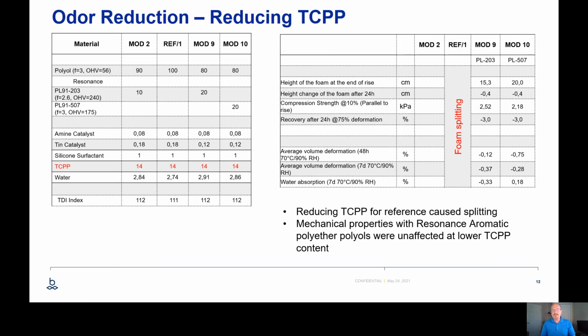So we went a little over 20% reduction in the TCPP because we figured it has to be a fairly large reduction in TCPP to affect the odor of a system, considering that TCPP has a relatively low vapor pressure, so it must take a lot to create any kind of odor. The only delta we saw with this particular system is the reference that we're using versus the 14 parts of TCPP began to split.